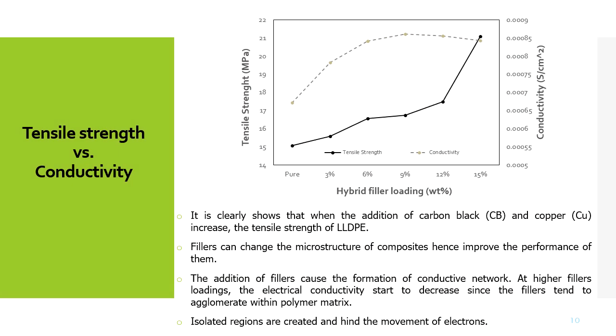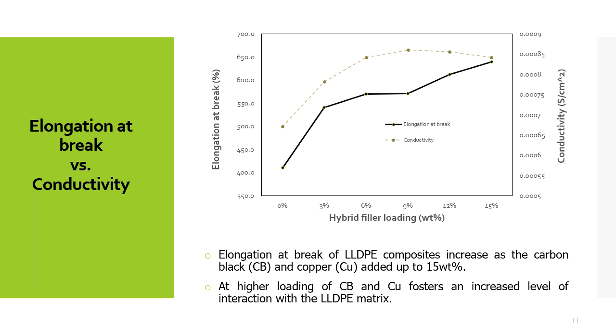In this case, if we look at the tensile strength versus conductivity, we can see that incorporation of the hybrid filler loading resulted in increasing tensile strength, and also as the amount of the filler loading increased, the conductivity also increased. Similarly, when we plot the elongation at break versus conductivity, we can find that the elongation at break also increased due to incorporation of the hybrid filler.